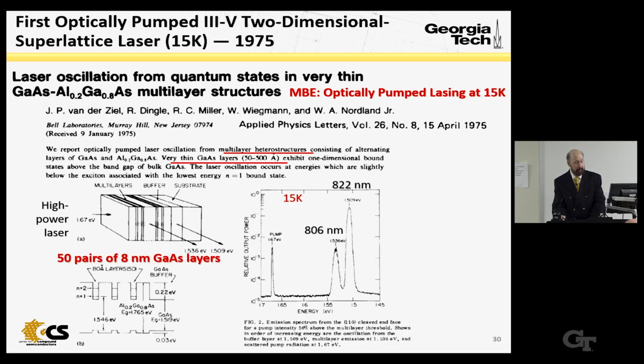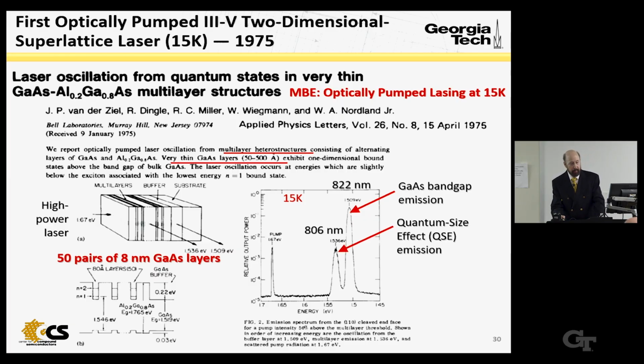As you can see, they had grown 50 pairs of 8 nanometer thick gallium arsenide layers with a smaller band gap, surrounded by larger band gap aluminum gallium arsenide, 20% aluminum layers. And they show, as you can see on the right side, an optically pumped spectrum at 15 Kelvin with 2 wavelengths, one for the gallium arsenide band gap emission of the substrate, and then the shorter wavelength quantum size effect emission of the superlattice.